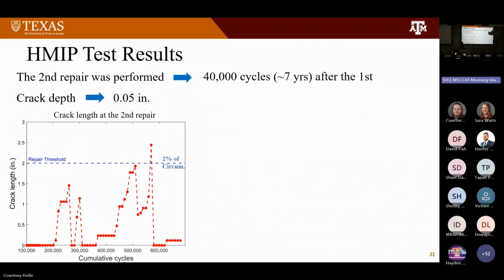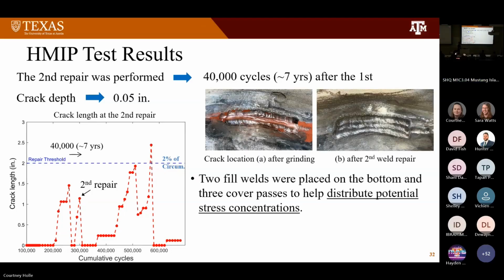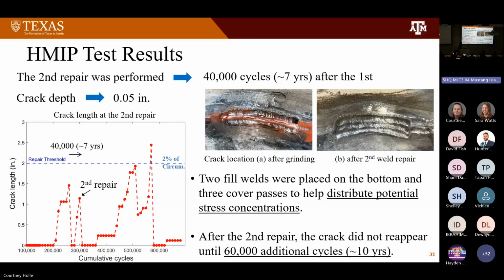The second repair was performed 40,000 cycles after the first. This time, the measured crack depth reached 0.05 inches, and the crack was located between the two cover passes. This time, we ground out the crack along with the previous weld and applied 5 weld passes, 2 fill at the bottom and 3 cover passes above them to distribute the potential stress concentrations. After this repair, the crack didn't show up for quite a while. Eventually, it did. The growth is relatively slow.